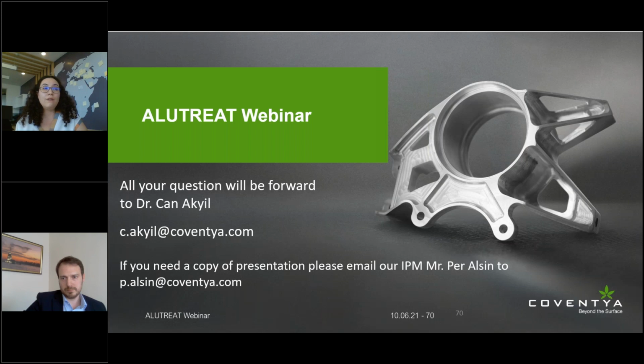Firstly, if you're doing a functional anodizing and the main request is wear resistance, maybe you should not use sealing at all, because the aluminum oxide wear resistance and hardness is much more superior than the aluminum hydroxide or other oxide structure. So that's why sometimes regulations say, do not use any sealing. But if it is not the case, if you need corrosion protection, if the service life is important, then you have to apply the right sealing.